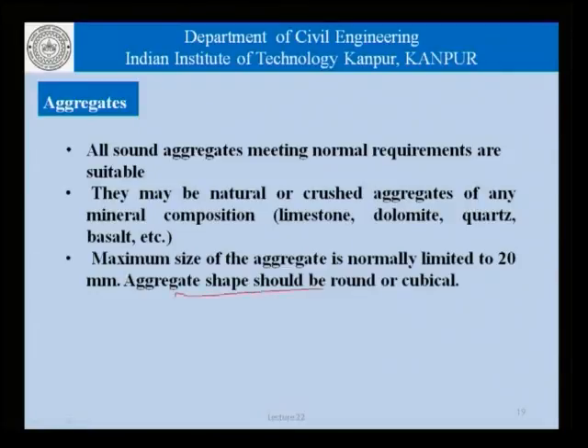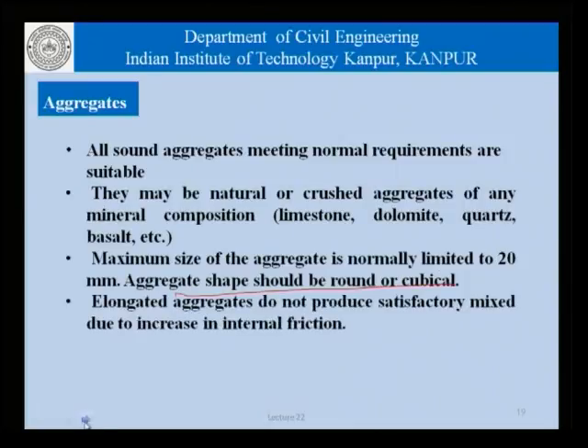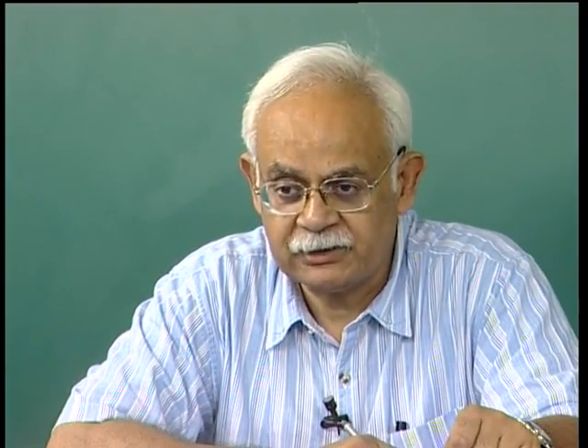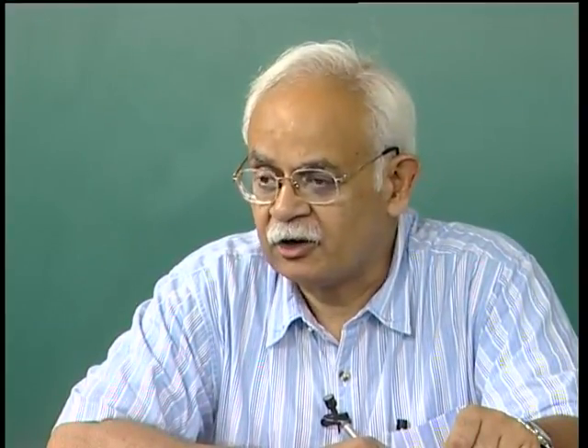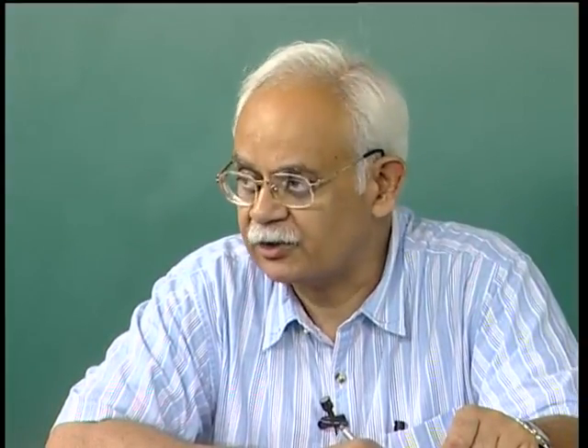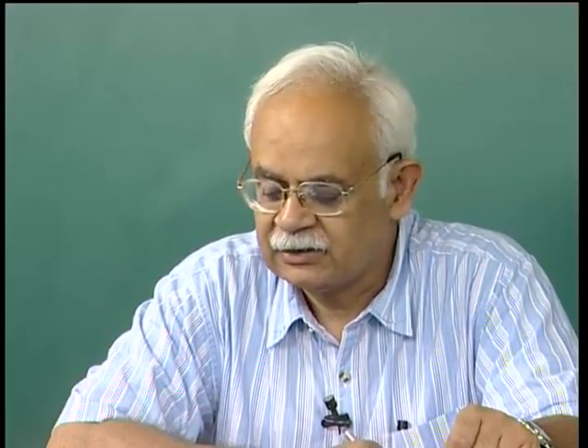Now, this is something which we need to be a little careful about as far as its use in self-compacting concrete is concerned, because elongated aggregates do not produce satisfactory mixes due to an increased internal friction and their tendency for aggregate interlock. And that is something which we would like to really watch out against when we are talking in terms of self-compacting concretes. In normal concretes, because we use vibrators, we have the possibility or a chance to break aggregate interlocks with the vibrators, but in self-compacting concrete we cannot afford that. Similarly, we cannot afford aggregate interlock in equipment or in piping and so on. So, we must ensure that as far as aggregates are concerned, they are at least rounded or cubical in nature.